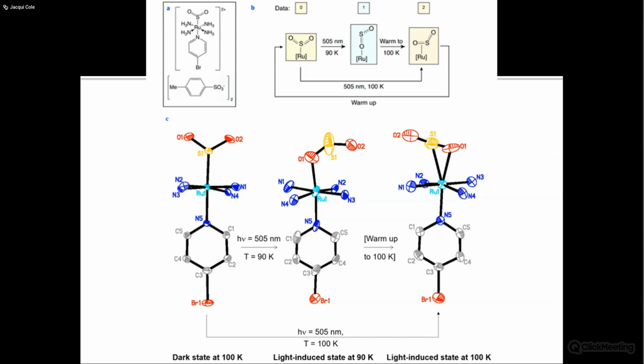And I actually got this by accident because I cooled it down to 90 Kelvin, because that's the lowest that the cryostat will go in my case. And I got this, and then I saw some color changing, which was unusual. And actually, it turns out that I had only just got it, because if you warm it up to 100 Kelvin, 10 degrees above that, it loses the oxygen-bound state entirely, and it goes to the side-bound photoisomer. And again, what's great about it is it goes to the side-bound isomer 100%, right? So there's still no dark state.